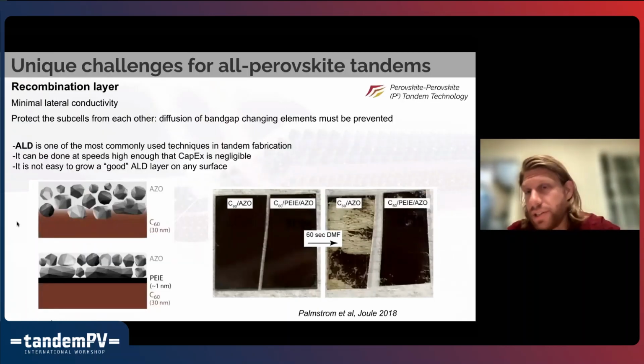Finally, the recombination layer is critical in the all-perovskite tandem. It needs to do several things. It needs to protect the two subcells from each other during processing, so that, if you're doing solution coating, one doesn't dissolve the first. But it also has to stop the two subcells from interacting during operation. As they get hot, we know that the elements in the perovskites can diffuse. If you're not careful, you can have bromine from one subcell migrating into the other subcell, and then your band gaps are changing during operation. That's extremely important to mitigate.